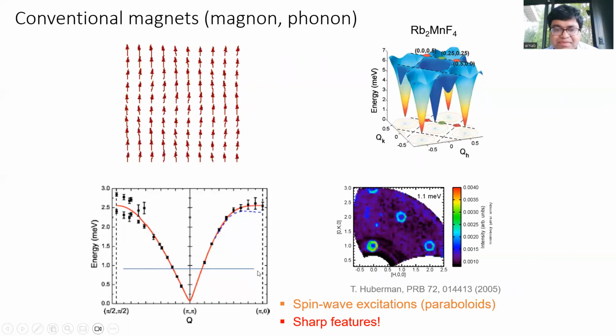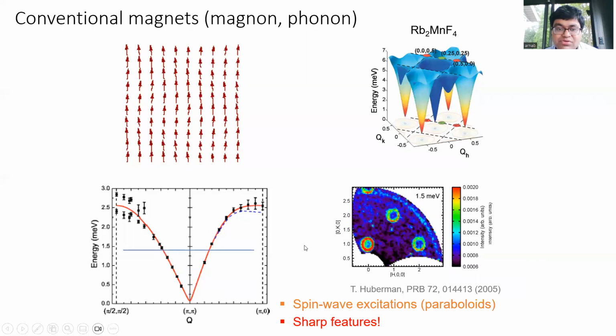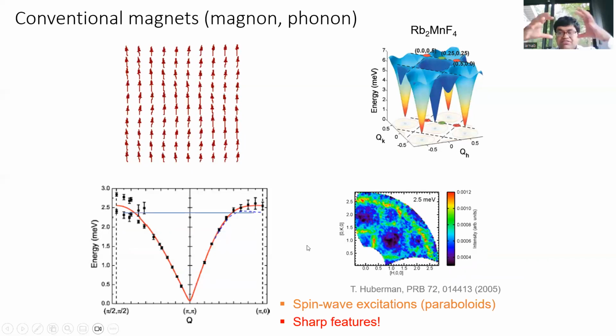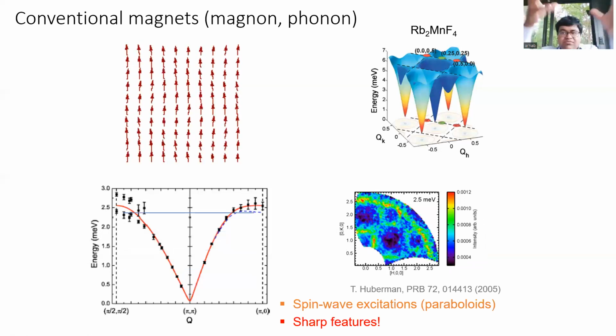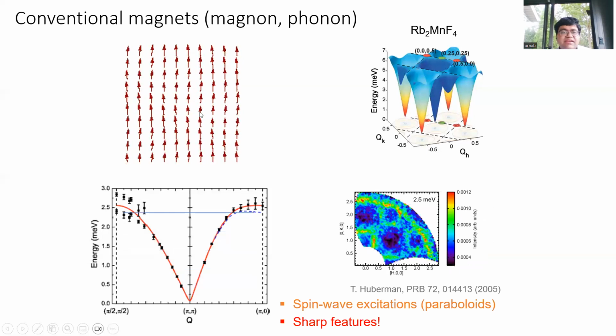As you see, you can make a cut at lower energies, and you will get these nice tiny circular features. But if you go to higher and higher energies, the circular features become larger and larger. So it's like a cone, which is flowering. These conical features are what you see when you have magnons, but that's not what you have when you have spinons. Magnons are basically the motion of the spins relative to each other, almost like a dance. But in a spinon, the spins completely flip, and then the flipped spin travels everywhere in the lattice.